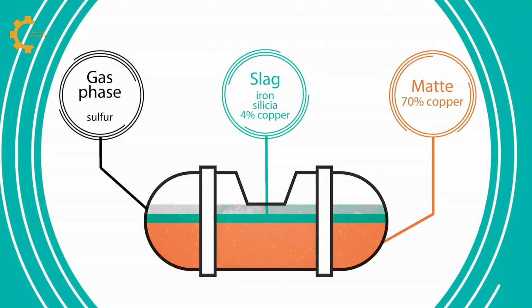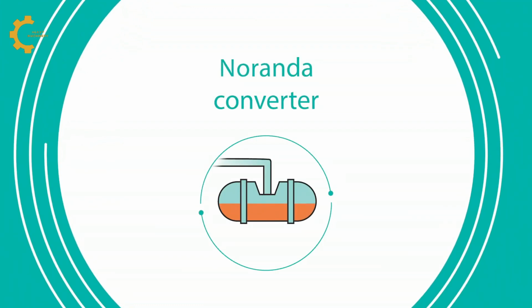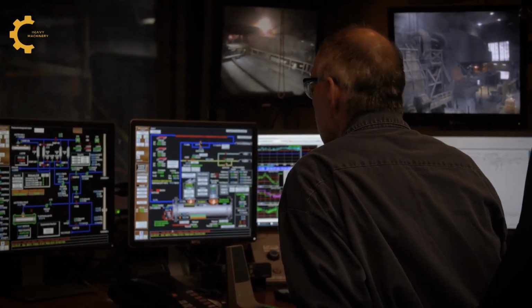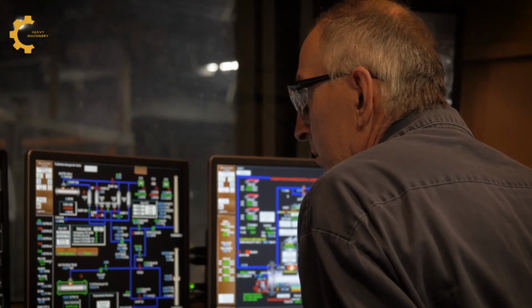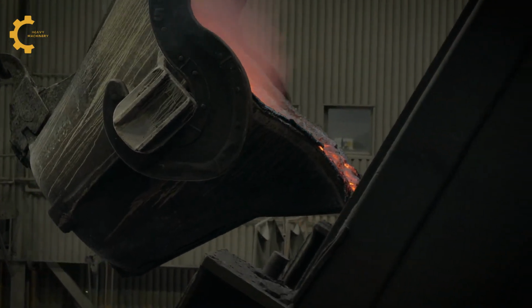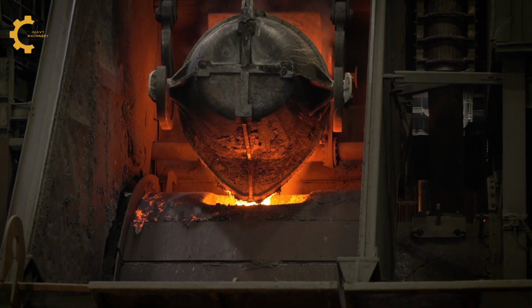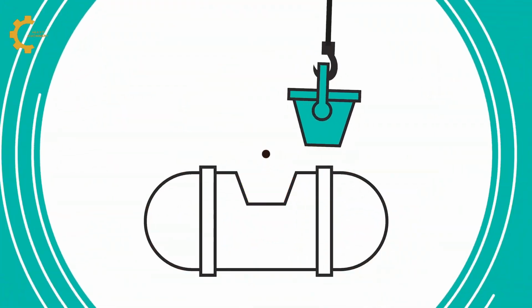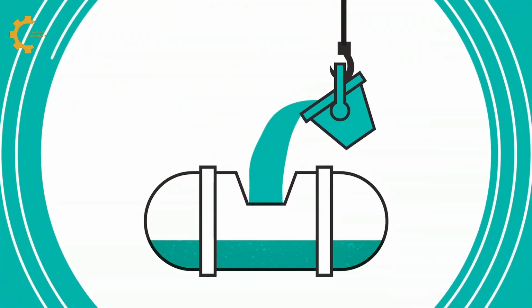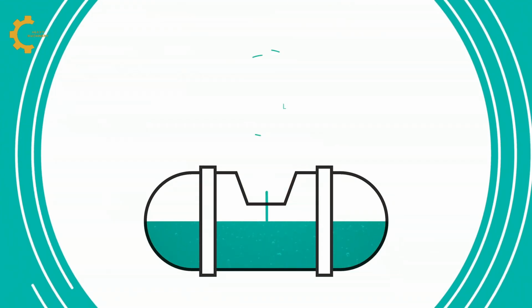known as matte. The matte, which is about 60 to 70% copper, is then subjected to further smelting in a converter furnace, where it is combined with oxygen to remove any remaining sulfur and iron. The result is blister copper, a product that is approximately 98 to 99% pure.